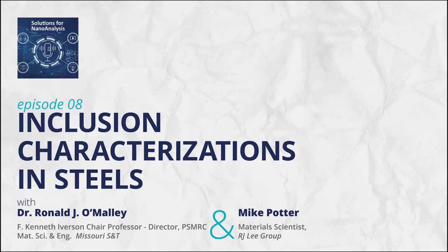So a necessary step in steel manufacturing is the deoxidation of those steels. And that's done through the addition of deoxidants, typically in the form of silicon, manganese, and aluminum. For a lot of the high quality steels, aluminum deoxidation, or sometimes called aluminum killing, is the dominant process that is used for deoxidation. Now, the downside of deoxidation is that when you add aluminum to high oxygen steel, you form a solid oxide product. And that product is an inclusion. It's dirt in the steel, if you will. And how we deal with that dirt, how we remove it, is actually very critical to the downstream objectives I just talked about.